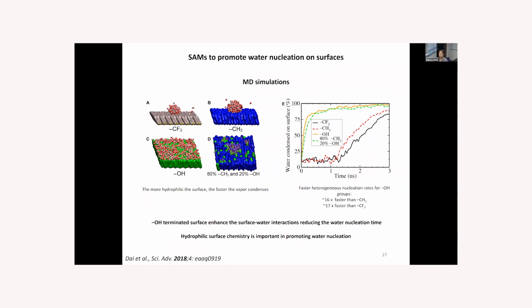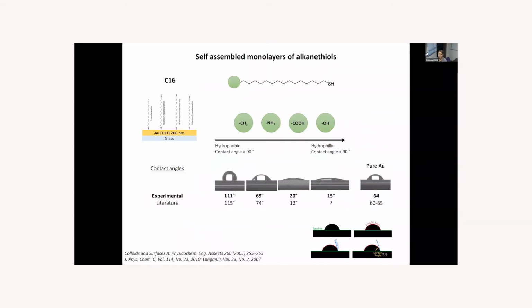They have seen that there was a faster heterogeneous nucleation rate for hydroxyl groups. It was 16 times faster than that of methyl groups and 17 times faster than that of the CF3 group. So to conclude, they say that hydrophilic surface chemistry is important in promoting water nucleation. For our self-assembled monolayers, we have chosen molecules with a carbon chain length of 16 carbons, and with different hydrophilic and hydrophobic groups, starting with the hydrophobic methyl group, and then the hydrophilic amino group, carboxylic group, and the most hydrophilic OH group.